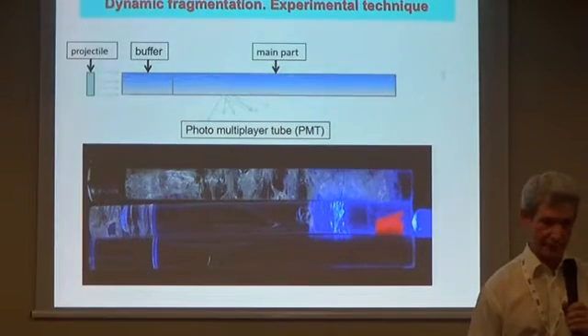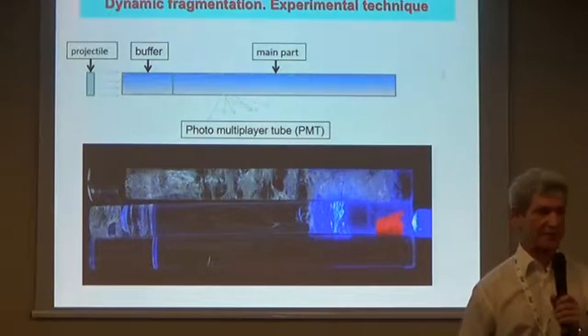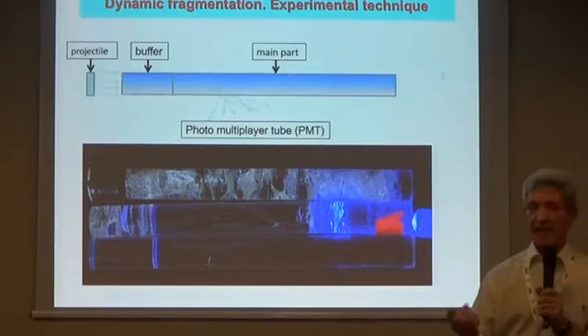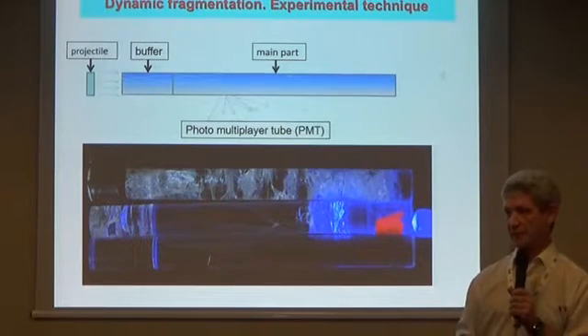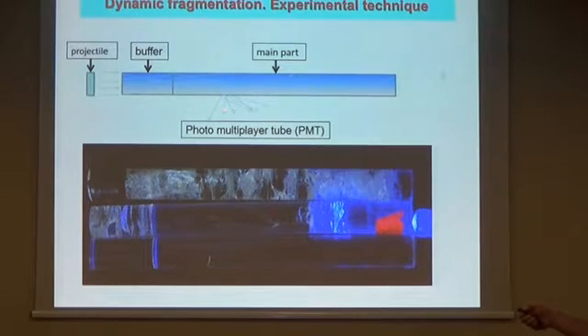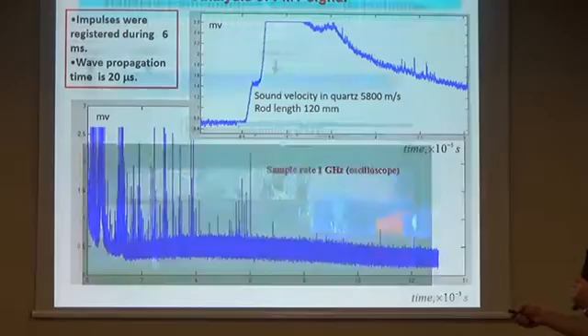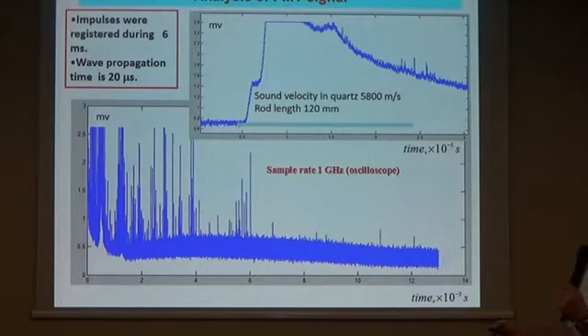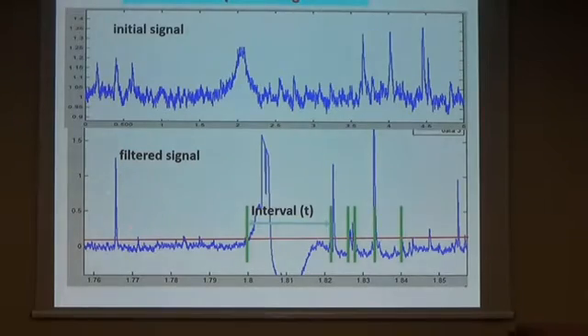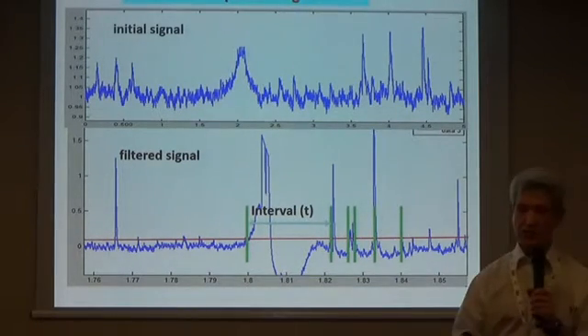And this kind of similar solution as a resonance excitation was also very important for us to explain some scaling effects due to fragmentation. For that goal, this type of experiment was carried out in recovery conditions, when quasi-brittle material, ceramics or fused quartz, were loaded by a gun, and in the recovery conditions we measured both stress characteristics and fracture luminescence. It means that due to the generation of numerous hotspots of failure, we registered a signal of fracture luminescence. You see, and after the filtering, we obtained the sequence which corresponds to nucleation of failure hotspots.